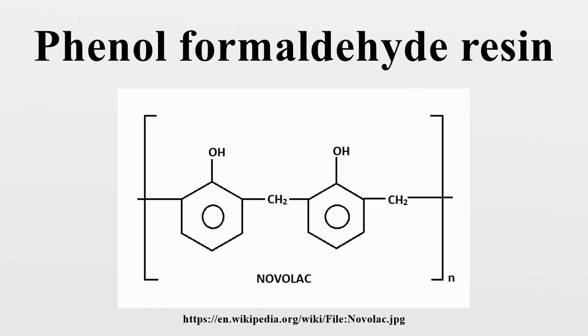Bisphenol F can further link, generating tri-, tetra-, and higher phenol oligomers. Novolacs are phenol-formaldehyde resins with a formaldehyde-to-phenol molar ratio of less than 1. The polymerization is brought to completion using acid catalysis such as oxalic acid, hydrochloric acid, or sulfonic acids. The phenol units are mainly linked by methylene and/or ether groups. Novolacs are commonly used as photoresists — see also photolithography. The molecular weights are in the low thousands, corresponding to about 10 to 20 phenol units.